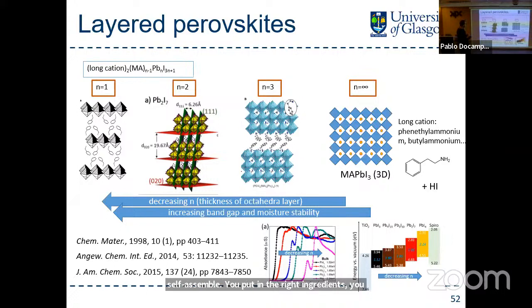So we looked at this particular data set. That's a phenethylammonium molecule. This one is a bulky cation that sticks between the lead octahedra. And we can control the number of octahedra if we control the ratio of the big cation to the structure that we're using. The more of the big cation that we put in, the thinner the octahedra become. So we can control that.